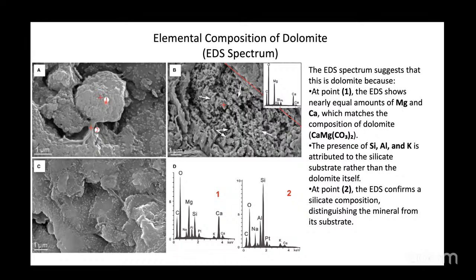Next, we see the presence of silicon, aluminium, and potassium here in the spectrum. These elements are typically found in silicate minerals, but in this case, they aren't a part of the dolomite itself. Instead, they are most likely coming from the silicate substrate beneath the dolomite sample. This tells us that while we're analyzing dolomite, the substrate is contributing additional elements to the spectrum.